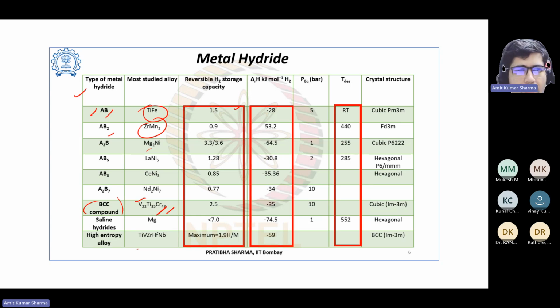As we have seen in the previous slide, if we change the metals, the composition, then the properties will change. You can see the reversible hydrogen storage capacity is changing: 1.5, then 0.9, then 3.3, then 1.28. The temperature of desorption is also changing, the enthalpy is changing. The structure is cubic, hexagonal, BCC. So you need to select the type of metal hydride as per your application, because the temperature, enthalpy and reversible capacity are changing.